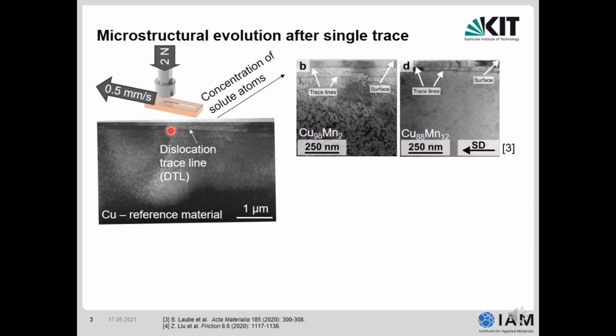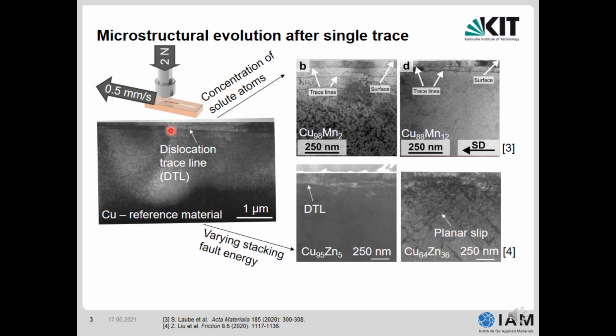So in the next step, we added manganese to copper to investigate the influence of the concentration of solute atoms. An increase in the manganese content does not change the stacking fault energy. So you can see here that there was still a formation of the trace lines, so there is not a huge influence of the solute atoms.